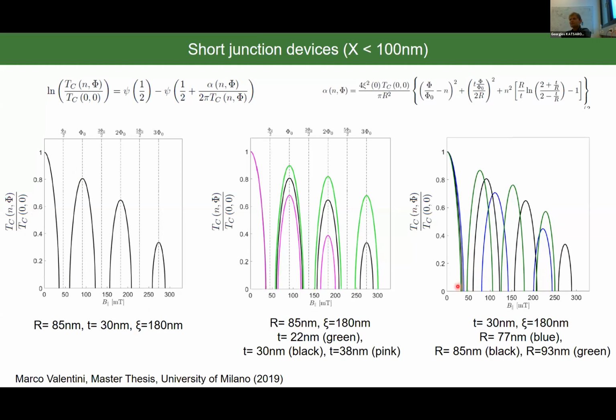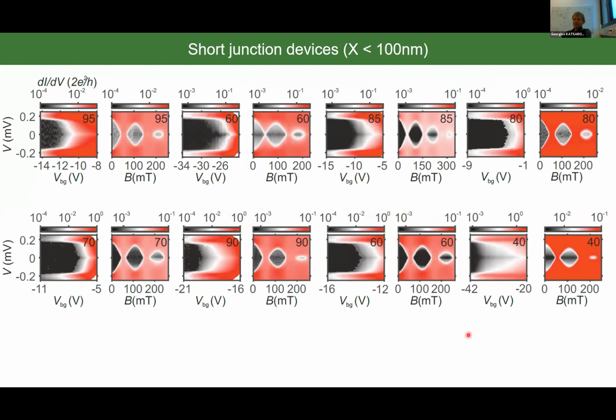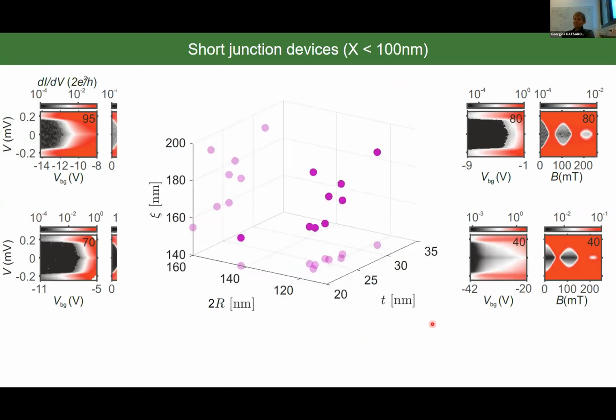So based on such a type of analysis, we take these 8 devices, we analyze them, and what you can see is that, as expected, they don't all have the same parameters. We are doing experiments, so the wires are not always of the same thickness, depending on where you are doing your device along the nanowire. So practically, you can see that we have a spread in the thickness of the superconductor, in the radius, and in the coherence length. So, as I told you, no Majorana zero mode in short junction devices.